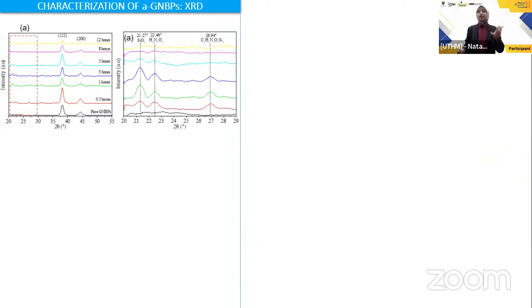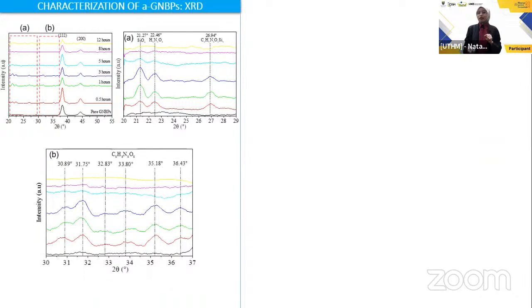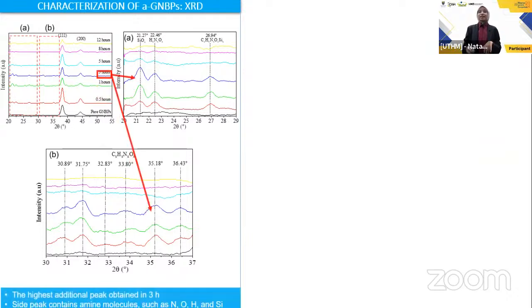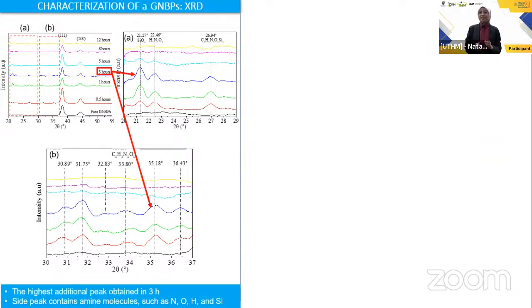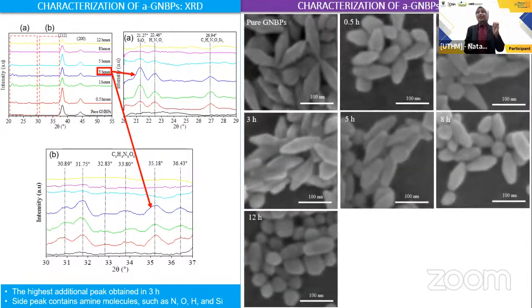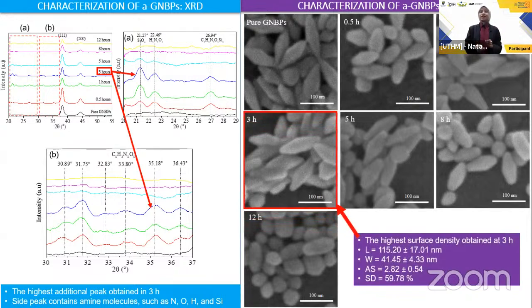Then we have XRD here. This is the XRD pattern for A-GNBPs. We can see here that there are additional peaks, consisting of amine molecules such as Si, N, H, and O, with the highest additional peak obtained at 3 hours, indicating that the highest interaction between amine groups and the surface of gold nanobipyramids occurs at 3 hours. Next, SEM. So these are the SEM pictures of A-GNBPs. Based on these results, the highest surface density is obtained at 3 hours with a value of over 59%.